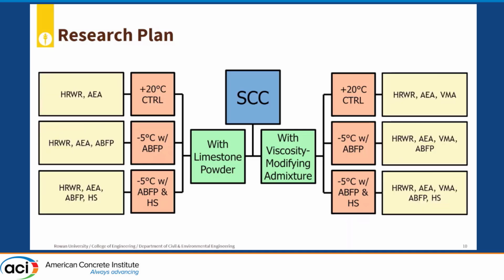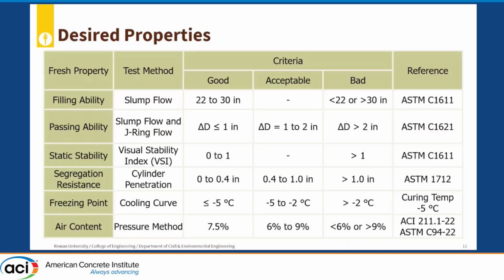Here are the admixtures used for each mixture. Notice that we only have VMA on half of the mixtures. We're using limestone powder as viscosity modifier on mixtures on the left. We have ABFP only on mixtures at -5 degrees Celsius, and we added hydration stabilizer on half of the mixtures at -5 degrees Celsius. We adjusted the dosages of these admixtures to achieve these desired properties.